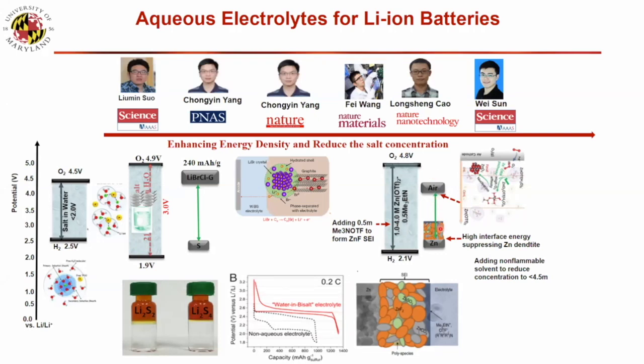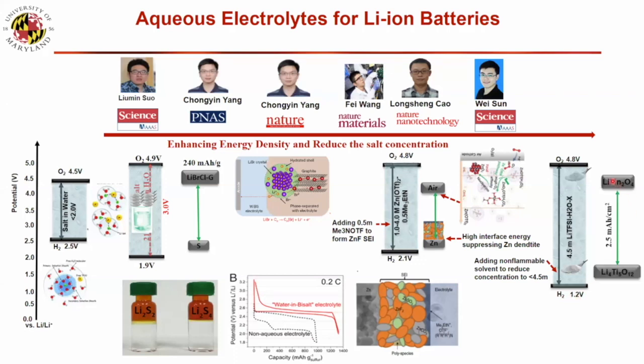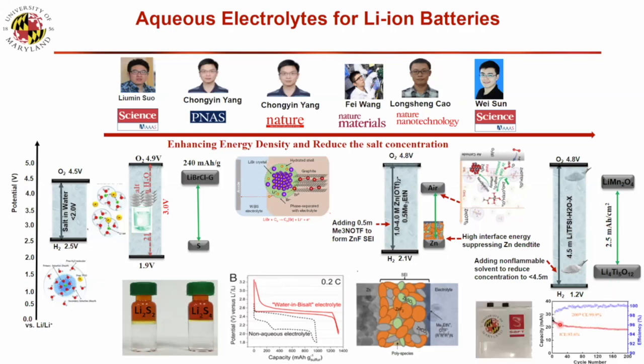Second, we also add non-flammable solvent into the water-in-salt electrolyte. In that case, we can reduce the salt concentration. So recently we added non-flammable solvent. We extend the window, the cathodic reduction potential, to 1.2 volt. And we demonstrate that with LMO and LTO, we can have 2.5 milliamp hour per square centimeter high loading and still cycle really stably. This is the data from a pouch cell, and we can cycle 200 times.